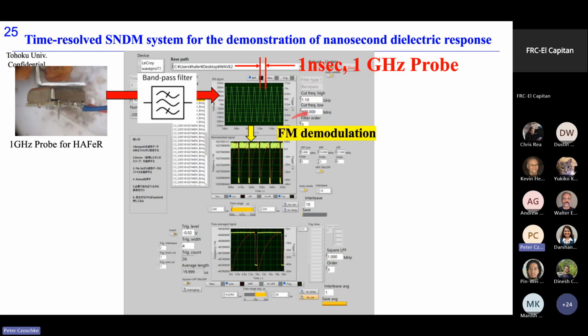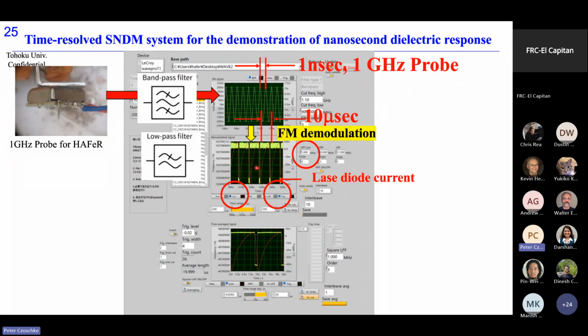And then we demodulate numerically and obtain this signal. In this case, to extract the low frequency part, we use a low pass filter numerically. This bright light green waveform is the actually measured laser pulse waveform, and this red line is the result using the low pass filter. So we set the low pass filter parameter like this, and in this case, the period is 10 microseconds. Anyway, this is a linear dielectric response.